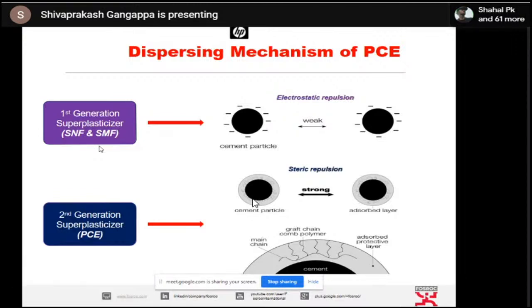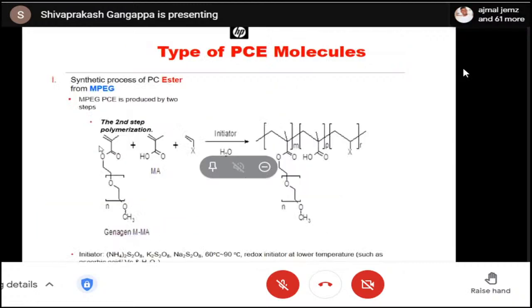Even if you add extra dosage, the water reduction will not take place. But if you use a polycarboxylic ether-based admixture, then you can bring down the water from 200 liters to 120. There are chances we may even go lower than this. So here is the choice of admixture. Whenever we go for high performance concrete, our objective is to use only polycarboxylic ether or an ester-based admixture. So that product selection has been fixed.